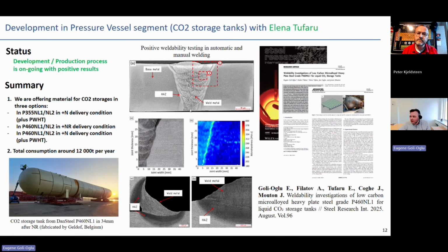And then normally we are testing in the middle of the weld, and then at the fusion line, fusion line plus 2 millimeters, fusion line plus 5 millimeters, and fusion line plus 20 millimeters, to be sure that each small section of the weld will still resist impact loads at minus temperature. And will guarantee a low temperature toughness both of base metal and of welding joint in total, like one construction, like one unit. And then we are also sometimes making more advanced investigation.